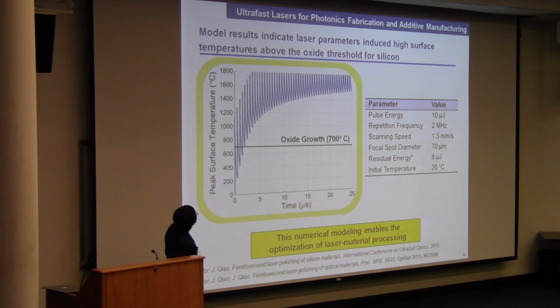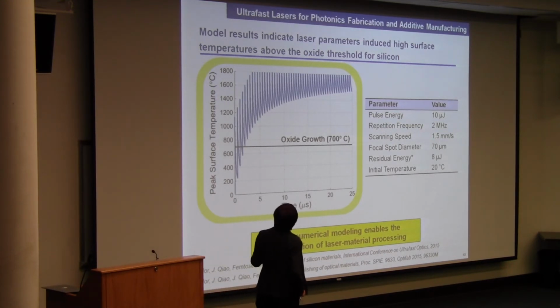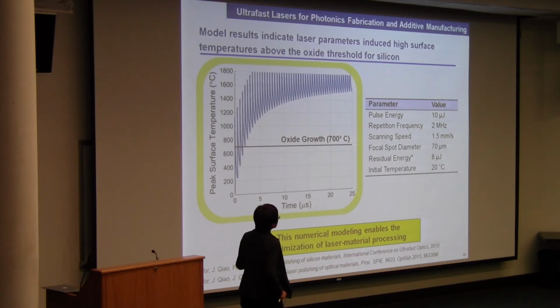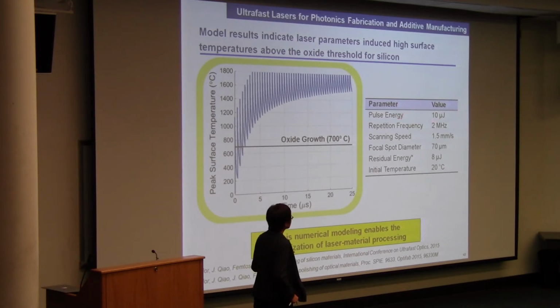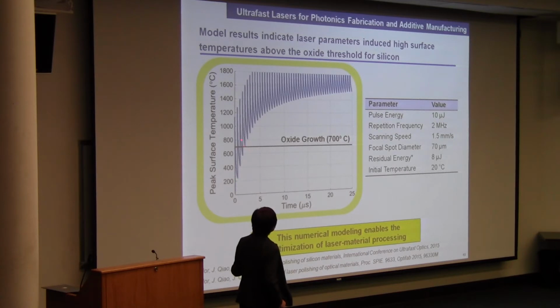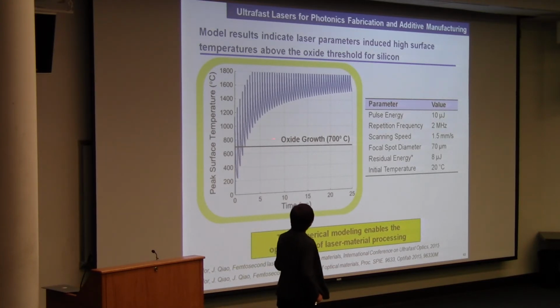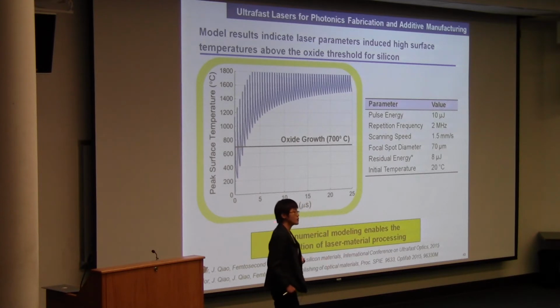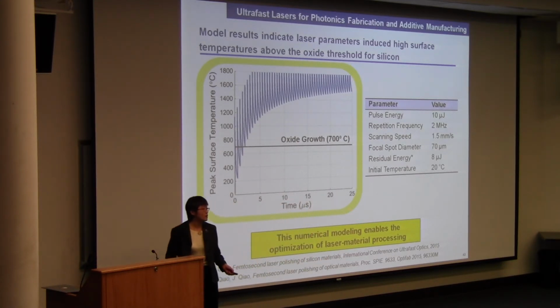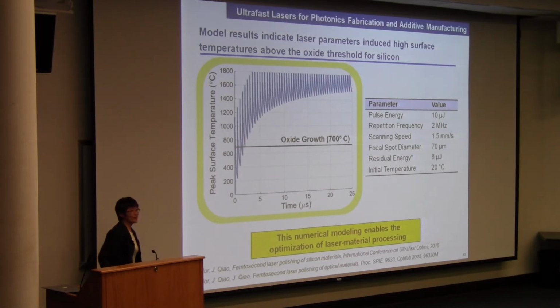So the model results indicate laser parameters induce high surface temperature above the oxide threshold in silicon. By plugging in the laser processing parameters, 10 microjoule pulse energy with a 2 megahertz repetition rate, 1.5 millimeter per second scanning speed, and 70 micron focal spot, we were able to see that after only 4 pulses, the surface temperature has exceeded the oxidation temperature, that's 700 degrees. That's why we were seeing oxidation in our material. And then this model enabled the optimization of laser processing. Lauren has presented this work at the SPIE Optifab to over 120 people as her first presentation. I thought that was pretty good.